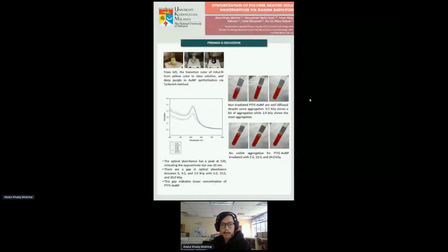Our findings: at the top left, we can see the color transition of chloroauric acid from yellow to a clear solution, and deep purple in the gold nanoparticle synthesis via the Turkevich method. We characterized it using UV-vis, and we found the optical absorbance has a peak at 520 nanometers, indicating the approximate size was 20 nanometers.